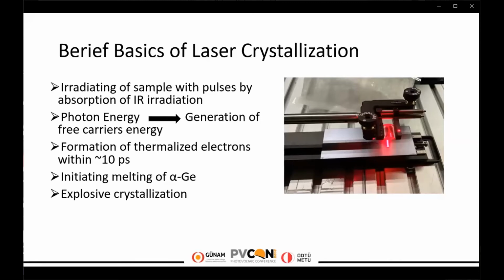When laser crystallization is performed, explosive crystallization occurs as an intermediate effect. The free energy released during crystallization is used first to sustain crystallization on the surface, and secondly to locally heat up the substrate.